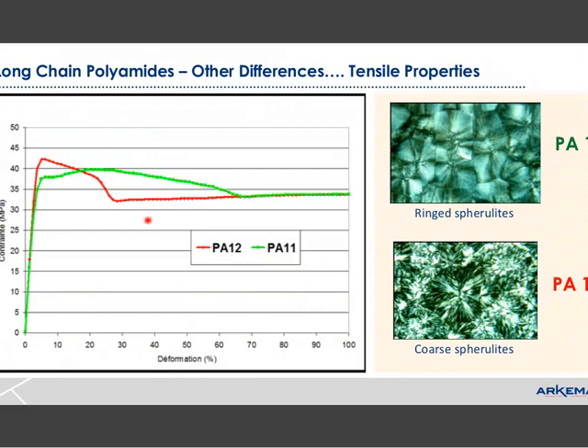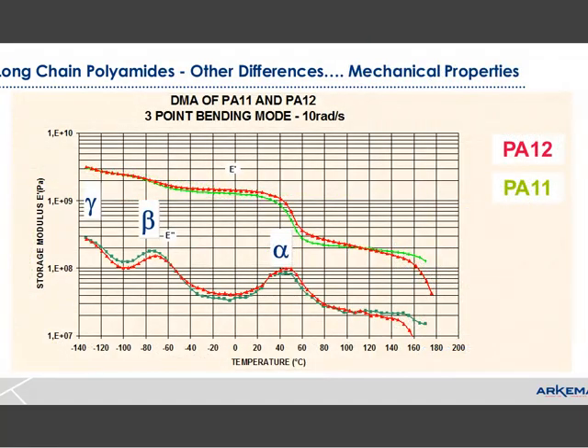And this slide right here on the left kind of explains part of the reason why. What we see is that for PA11, if you're looking at tensile properties, during the neck-down process, it takes much more energy to reorganize the crystal structure in that polymer than, say, PA12. And if you look over here on the right, you'll see that the crystal structures are different. And with PA11, reorganization of these ring spherulites takes much more energy than the coarse spherulites. And this gives the different tensile properties and, more importantly, the improvements in impact.